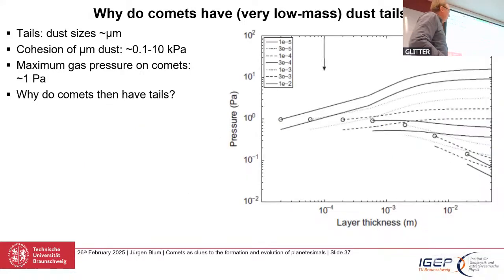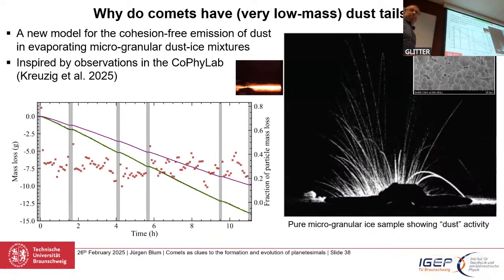But if you're looking at the gas pressure, which in a classical model by Kührt and Keller 94 is responsible for driving out the particles, releasing the particles against their cohesion, then if you're doing a model like we did back in 2012, but all the new models come basically to the same results, the canonical pressure you're getting is 1 Pascal. So short by at least 3 orders of magnitude. So that's the question: why do comets have tails? Until a few years ago, I had no answer to that, but now I do.